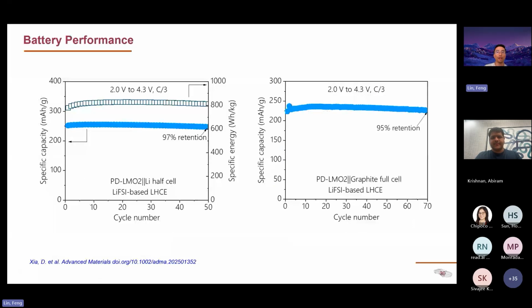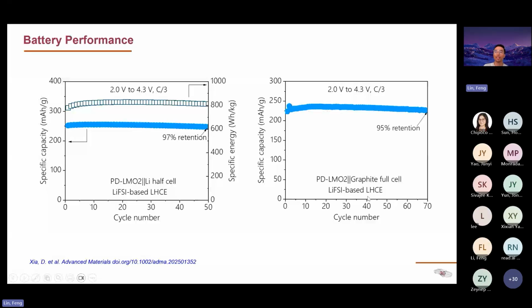This is a full cell. This is half cell on the left-hand side. We incorporate a localized high concentration electrolyte into our investigation. On the right-hand side, we have graphite full cell. They perform quite stable over 70 cycles. But I have to say that for longer term cycles, we still get some problems.